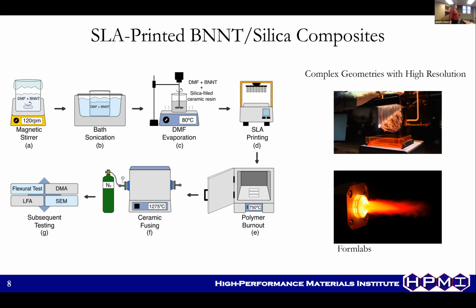Based on these results, we actually, as of last week, have some promising results with silicon carbide. So silicon carbide as the ceramic, swapping out the silica. So this was just something to prove feasibility. So, and then did the SLA 3D printing. You can see the SLA 3D printing here, the complex geometries with very high resolution, polymer burnout at 750C, and ceramic fusing in nitrogen at 1275. And then we did some flexural testing, DMA, LFA, which is thermal testing, and SEM. So, and through the previous study, this all builds on itself. So through the previous thermal decomposition study, we know that our BNNTs are safe at these temperatures. So we don't expect any degradation to happen during the processing.